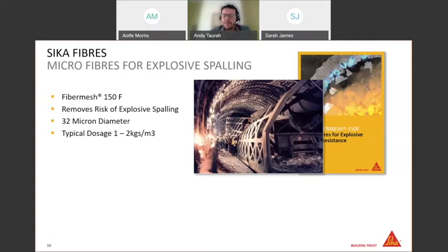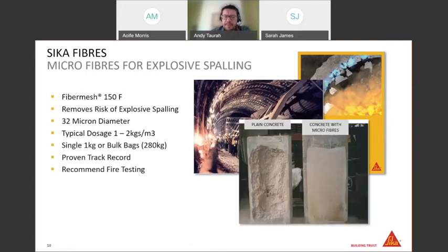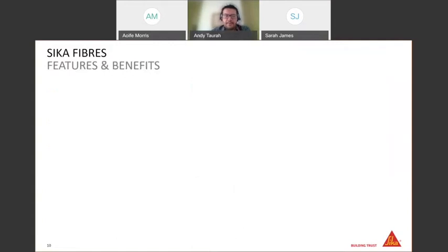Dosage, typically 1 to 2 kgs per cubic meter. We do a range, and we do a single kilogram bag, and we also do the large 280 kg bulk bags for all the fibre dispensing machines, which are often used on these types of projects. Proven track record we have, and we always recommend fire testing up front. Those of you that have witnessed the effect of explosive spalling, I'm sure that memory will be ingrained for a lifetime. It is quite a scary scenario to be involved with.